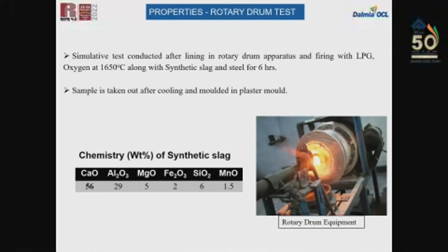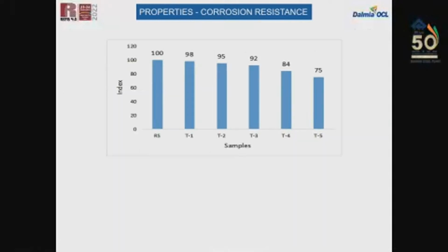This is the rotary drum test with a synthetic slag. Here in that index, where there is a corrosion index, we have seen that the corrosion index is also decreasing from the virgin material as we increase the recyclate. But after T3, that is when we cross the 30% limit, it decreases to 84%. That is almost a 16% decrease, whereas up to 30% it stays in the 90s range.